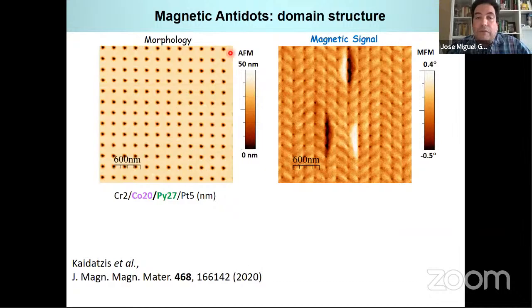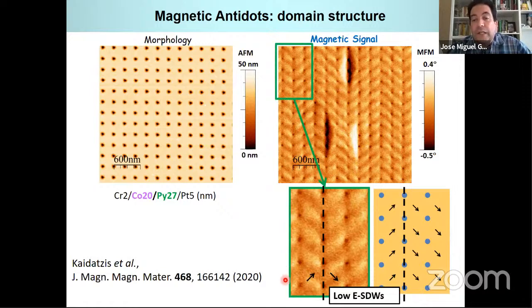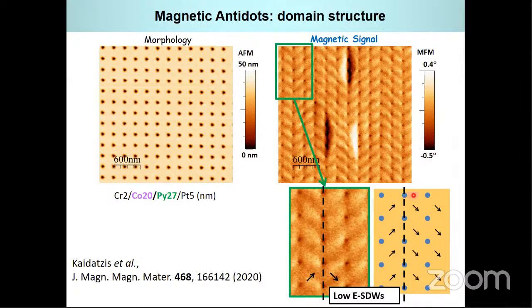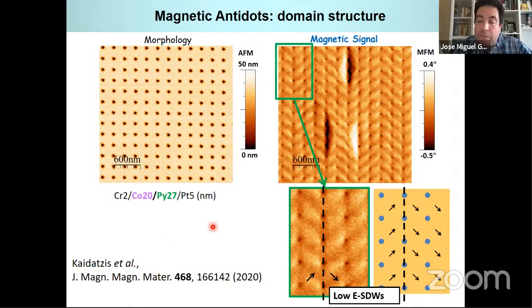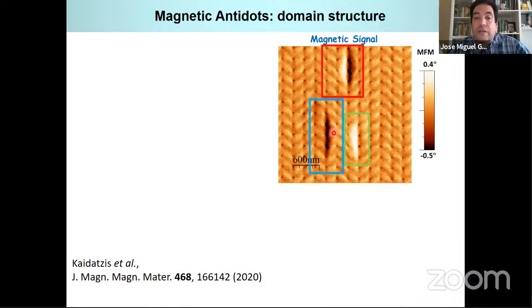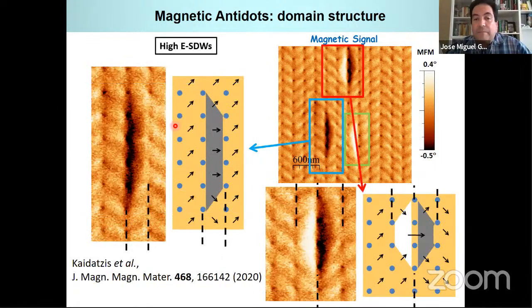In particular, you can see the topography on the left, magnetic signal on the right, and there are two different regions in the magnetic landscape. On the one hand, we have these regions with a tiny contrast, and you can see in the unit cell, we have bright contrast, dark contrast, so the spins are pointing like this. In this case, bright and dark, here is pointing like that. So in the middle, we have what is called a low energy superdomain wall. So this is the structure of this region. But we also have other regions which exhibit a strong contrast, either single contrast, dark or bright, or dipolar contrast. It means that there are a lot of magnetic poles accumulated in those regions. And the ones with only one kind of contrast, those are the regions where two low energy superdomain walls end.